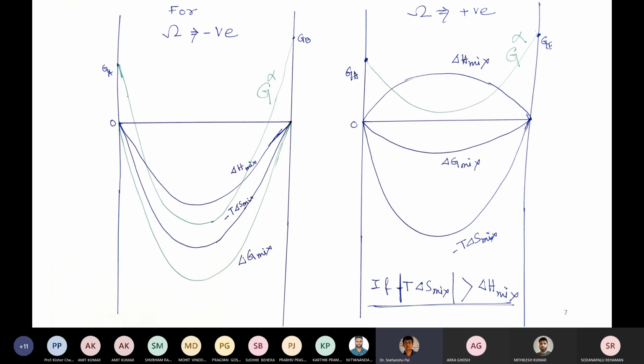So why is it not true? If you take an example of copper and zinc, zinc dissolves in copper very much, whereas copper does not dissolve in zinc. So A dissolving in B very well does not guarantee that B is going to dissolve in A in a very good fashion. We try to give a logic based on the valency, the Hume-Rothery rule and all those things. But if that is true, the interaction between A and B atoms is different from one end of the phase diagram to the other end. That we have already captured in the subregular solution model.